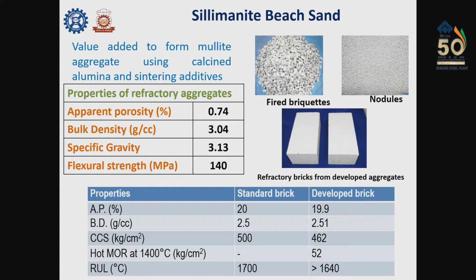We did value addition, converted it to mullite. The problem with that is that as it is a very pure material, it's very difficult to sinter. So we judiciously selected the sintering additive to enhance the sintering or densification behavior. We did it both through the briquetting route as well as the nodulizer route, and you can see that we could achieve a specific gravity of 3.13, very close to the pure mullite phase, and the BD is 3.04.